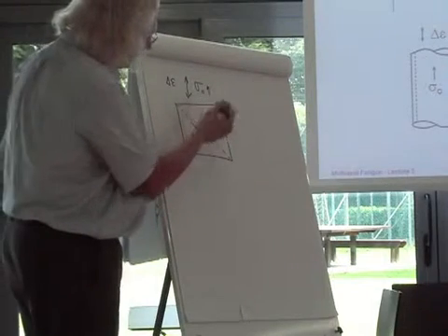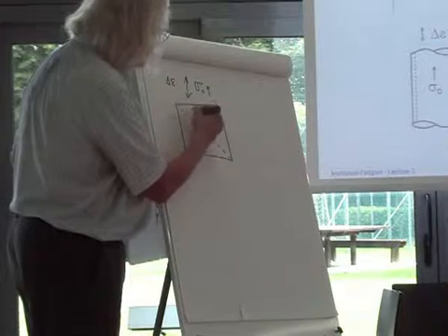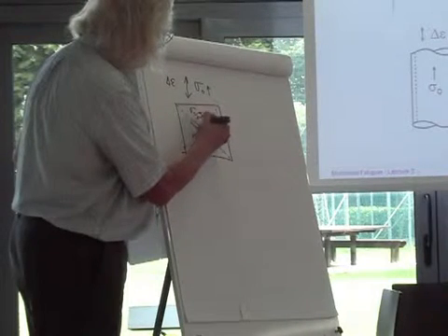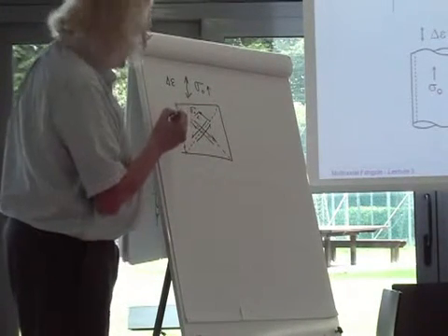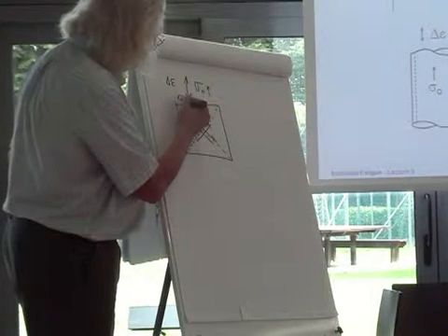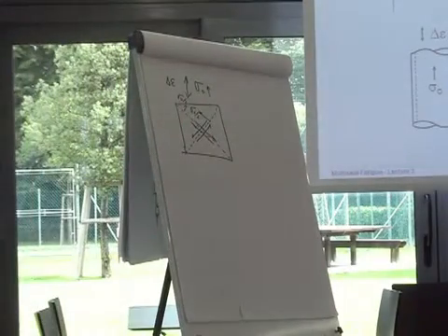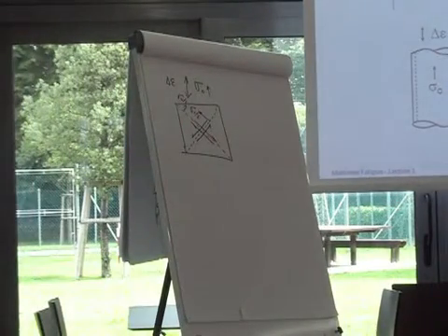And that mean stress will resolve into a stress here of the mean stress divided by 2, right, on that plane. And it will also resolve into the same mean stress, sigma 0 over 2, on that plane. Right? So that's the state of stress and where all the action will be.